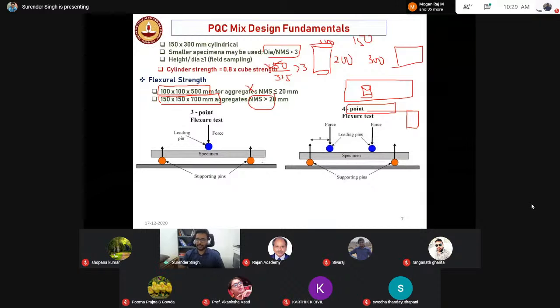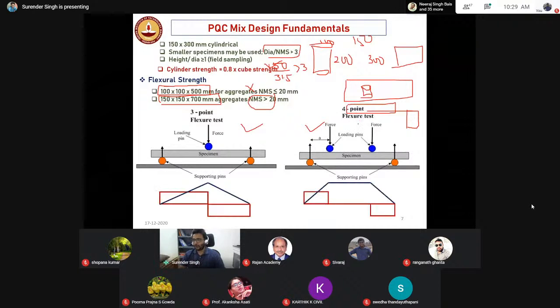And the other thing I have seen, I discussed it yesterday also, in the structural laboratory you will have a 3-point bending apparatus. In the transportation laboratory we have the 4-point bending apparatus. When you are designing your structures, it is 3-point bending. When you are designing your pavement, it should always be the 4-point bending test. Why? Because our pavements always fail in pure bending, where there is no shear force. But if you are evaluating the strength by the 3-point bending, you can see there is some shear force also at the mid level. So that means it is not okay when you are going with pavements.